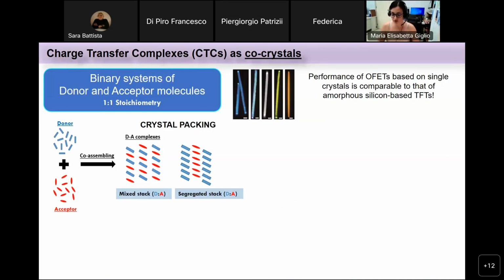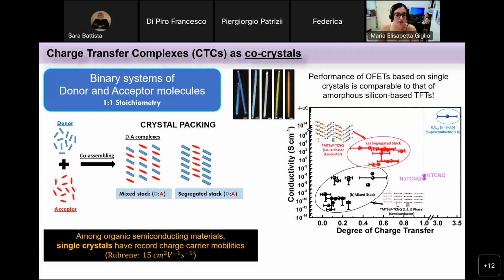Because when we think about a transistor and small molecules, we want to have crystalline films. So basically, the charge transfer complexes can crystallize into different configurations. One is the mixed stack configuration, and the other one is the segregated stack, and it occurs by co-assembling of the donor and the acceptor molecule. And what is interesting is that the performance of transistors based on these single crystals is comparable to the ones of the amorphous silicon-based transistors. So, for example, among a variety of organic semiconducting materials, single crystals have record charge carrier mobilities that are really high. Rubrene is an example. We reached field effect mobilities of 15.